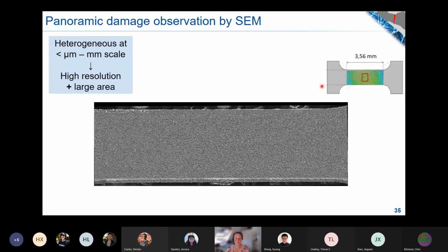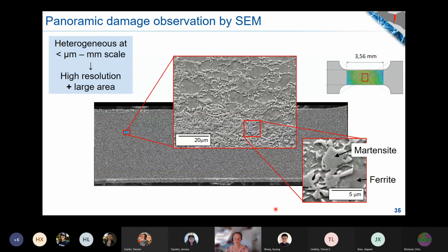The setup that we use for this is that we look at a tensile test sample, and this is a few millimeters, for example, across, and then we set our microscope to take lots of individual images, and at the end of the day, we stitch them together in one panoramic image where you can then, at every point, zoom in to about this level of resolution. That's the one that looked useful for us.